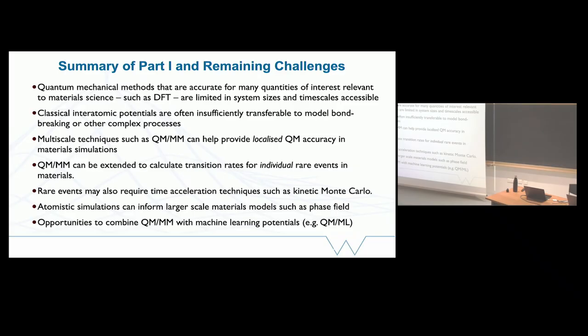No, it's a good question. Phase field is a good example here because there is no true scale in the phase field model. So it's perfectly possible to bring the phase field right down to the atomic scale or to the quantum mechanical scale, and then directly fit the free energy term that you use in a phase field model to effective observations from the atomistic model. You can't quite directly fit to the energies and forces because you want to include entropic effects, which will no longer be there once you have your phase field model. But you could fit to the results of dynamical simulations at the atomic scale. This hasn't been fully exploited, I would say. I think it's an important area that more work could be done in.